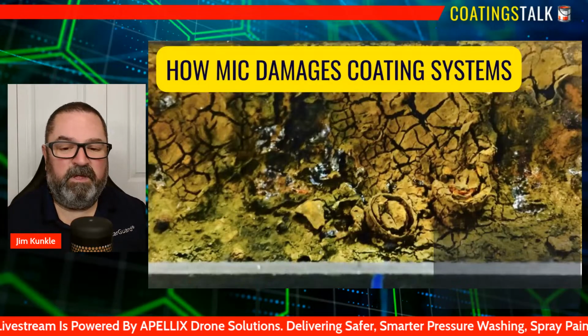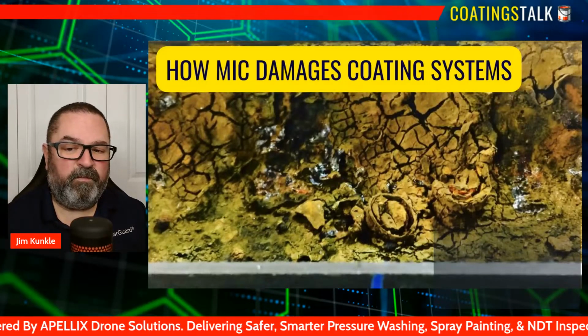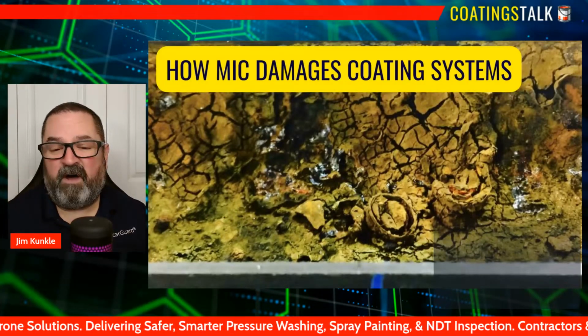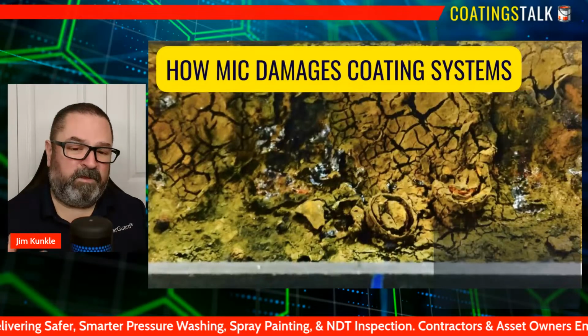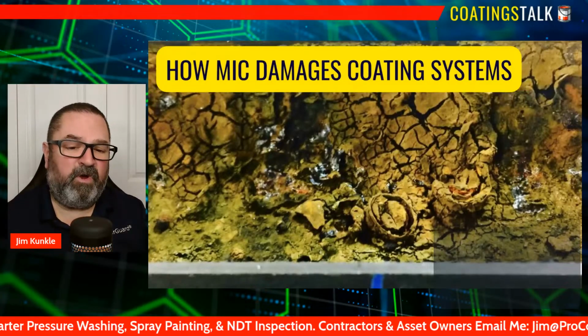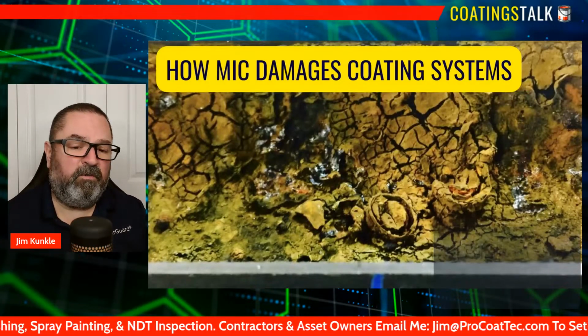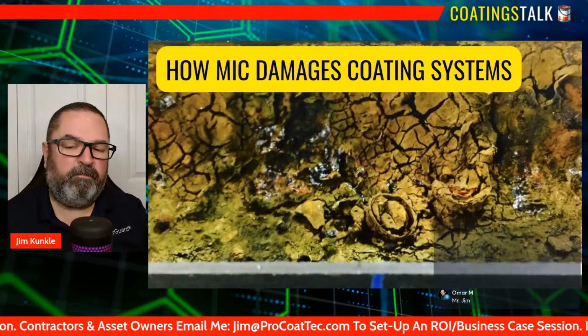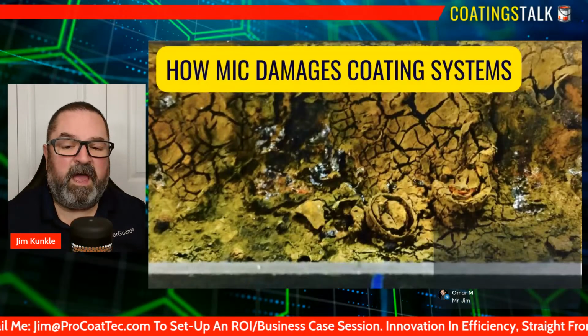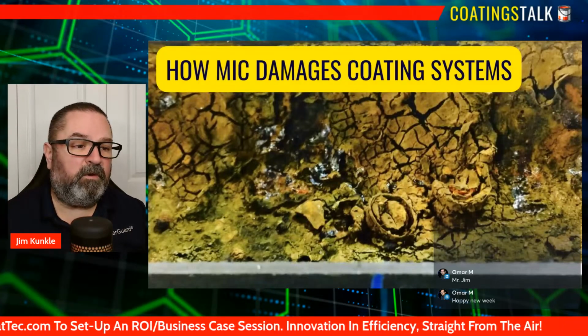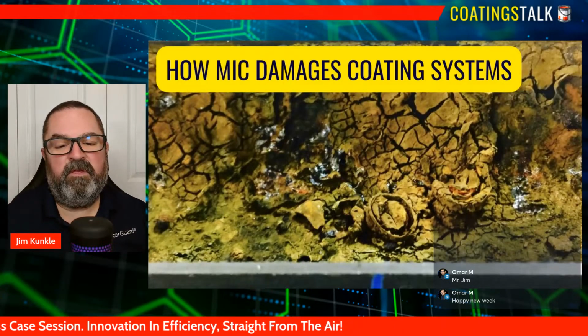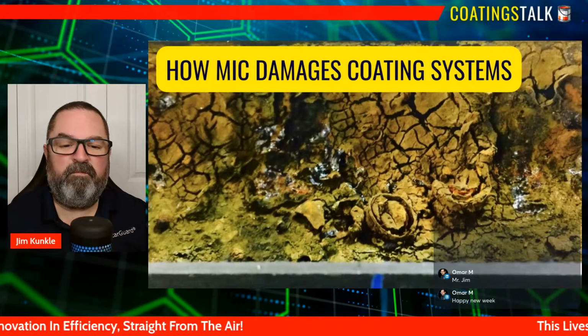the coating system. Inside that film, microbes generate acids, sulfides, and other metabolites that attack both the coating and the underlying metal. What looks like discoloration or small blisters on the surface may actually be the visible tip of a highly active corrosion cell fueled by microbiological activity beneath the film. As the biofilm matures, it disrupts the protective functions of the coating.